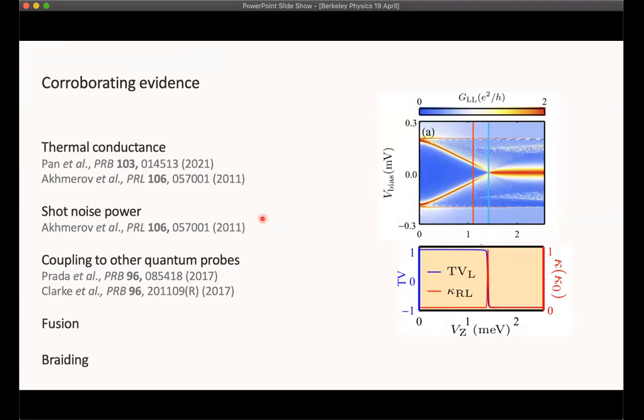Additionally, shot noise power should indicate the presence of a topological phase transition. And there are some suggestions that coupling these Majorana quasiparticle ends of wires to other quantum probes like quantum dots can indicate the presence or possibly the overlap of Majorana modes. And finally, I would say that the two strongest pieces of corroborating evidence for the presence of Majoranas and the existence of this topological phase would be to then take those Majoranas and either fuse them or braid them. This would really be the most compelling evidence of having built a not just observable but manipulatable quantum system.